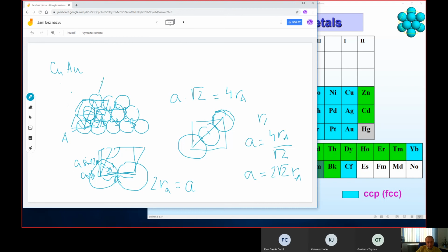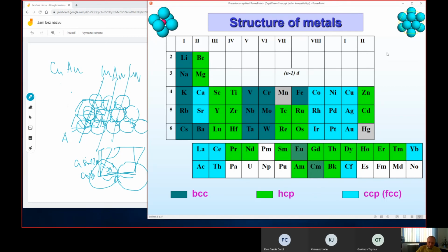We can have a row of copper atoms and a row of gold atoms, and again Cu and Au and so on. So this is an ordered structure, also a compound, which is based on the ordering of substitutional defects, which are 1-to-1 in the stoichiometry.